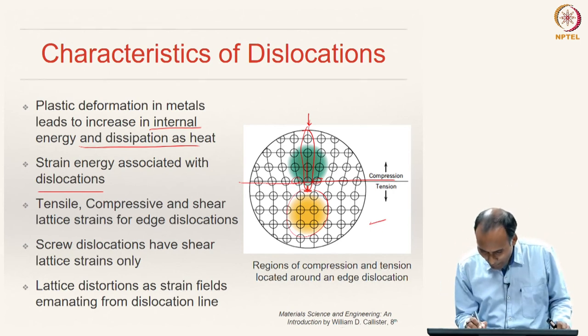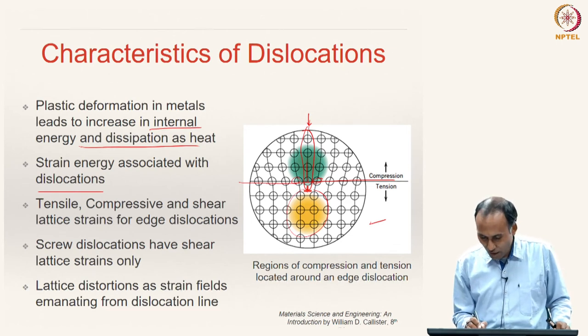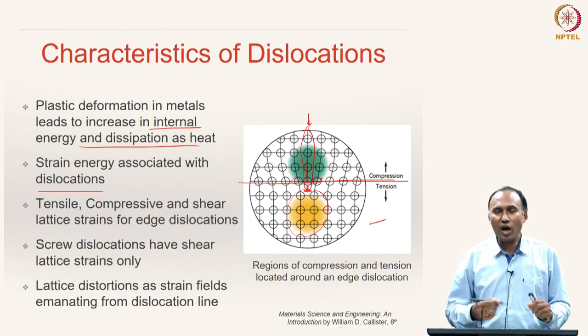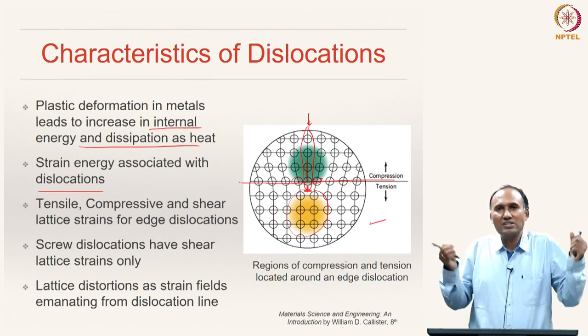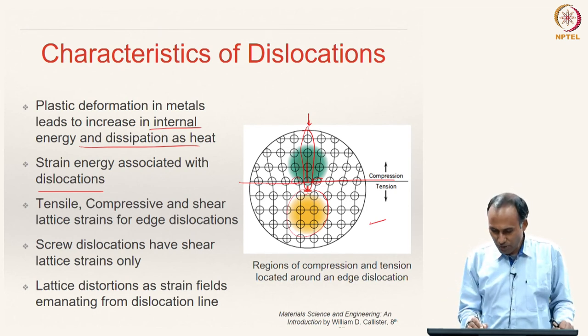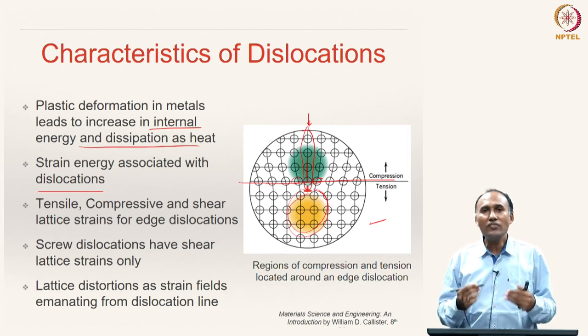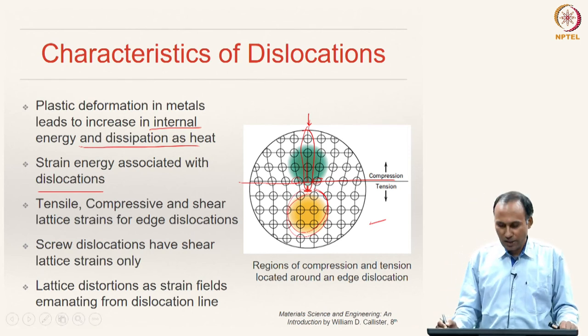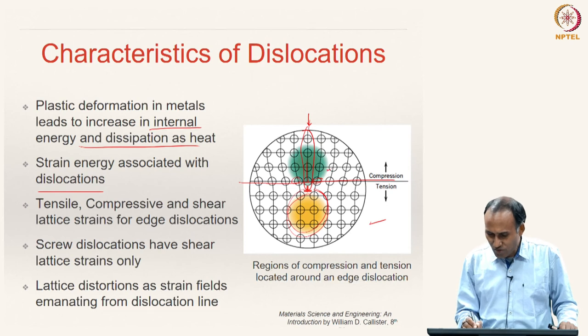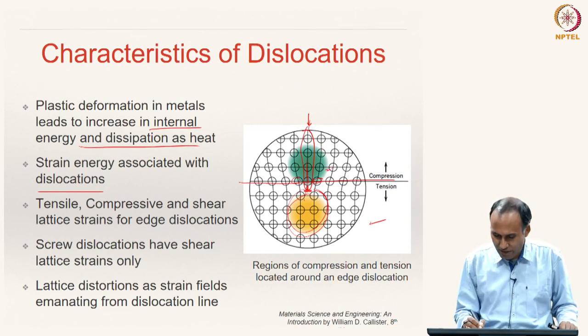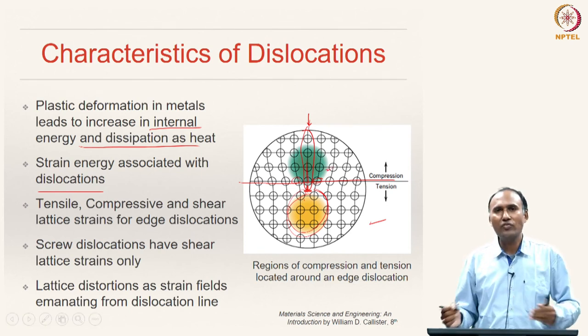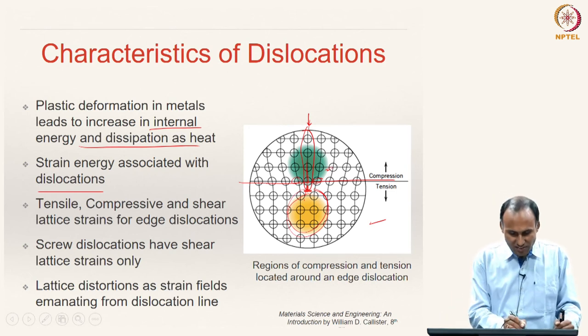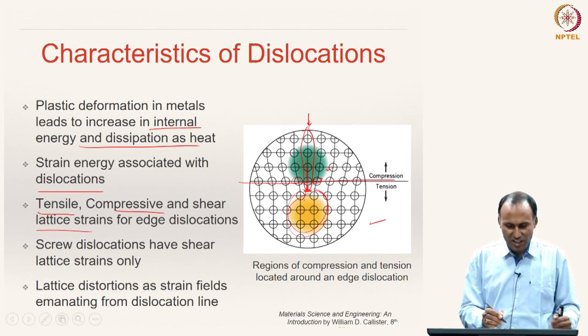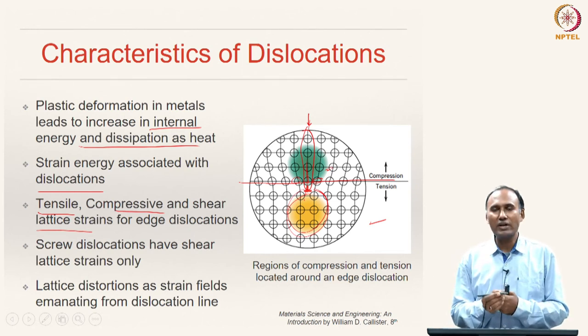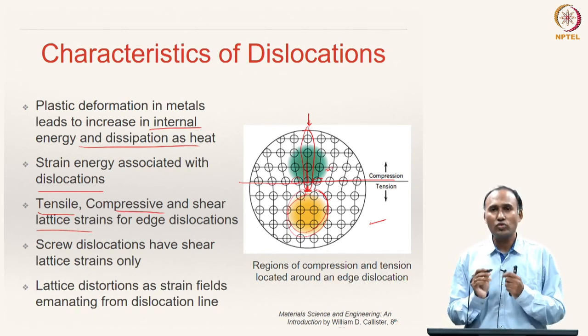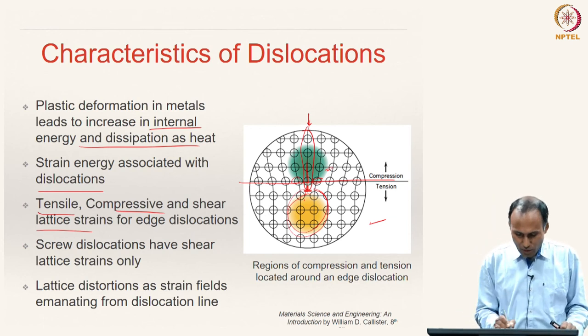and as a result the atoms just above the dislocation line, or adjacent to the dislocation line, start feeling a state of compression because they are squeezed together, and the atoms below feel a state of tension in the case of an edge dislocation. The atoms elsewhere, not immediately above or below, might feel a state of shear. So tensile, compressive and shear lattice strains are possible for an edge dislocation, whereas for a screw dislocation you will only have shear lattice strains.